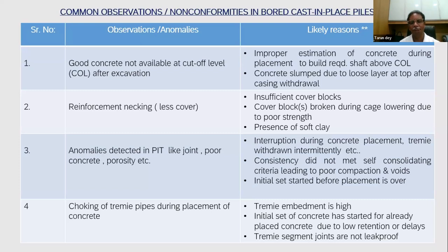Reinforcement necking. Sometimes you see after excavation or through a PIT, the information comes that there is a necking at 10-meter depth, 19-meter depth. So what could be the probable reasons? Insufficient cover blocks, broken during lowering of the cage due to poor strength. When you lower the cage, you strike here and there and the blocks get broken.